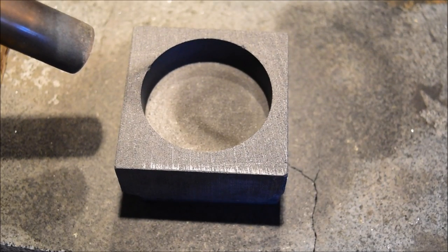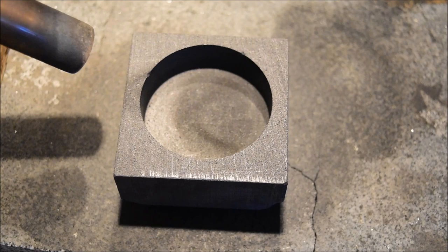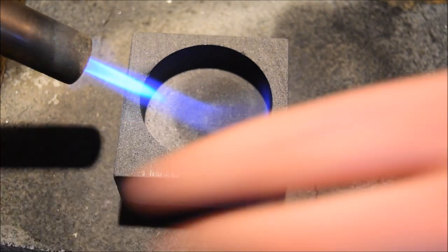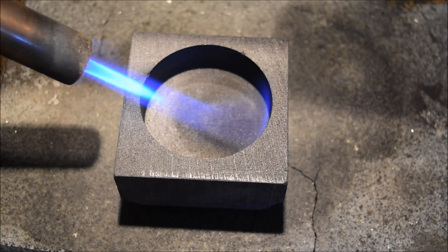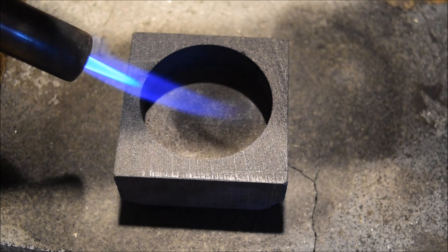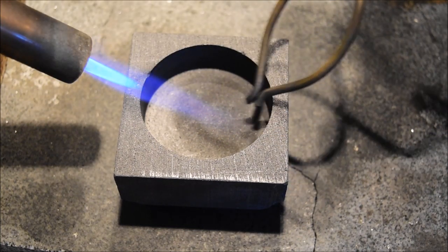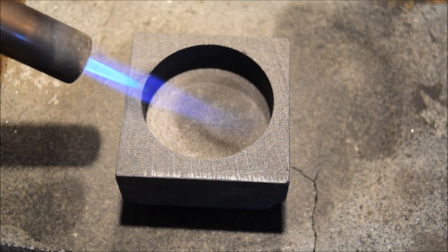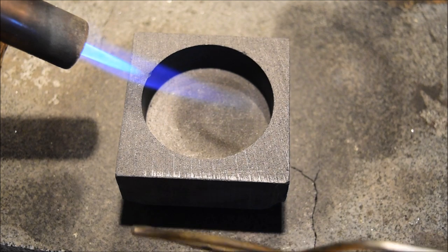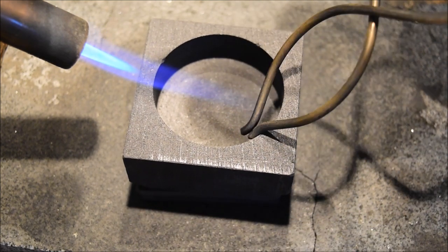We're back, and it's like a Sunday morning here — so dark and dank and horrible outside. I've had to turn the light on to get any kind of vision on the camera. Silver is pretty much up to temperature and I've been heating the mould already. I'm going to get the blowtorch back on because that's how I create my lovely ripples — I turn it down so we've just got a gentle flame. Getting a lot of heat in the mould is good because it helps the silver settle in the base better and you tend to avoid air pockets.